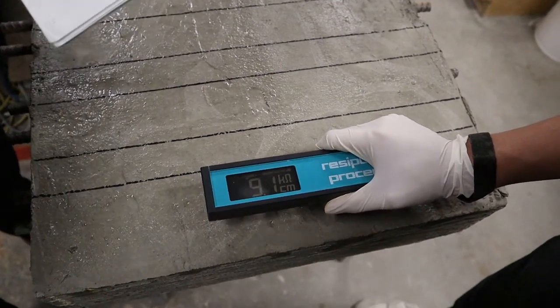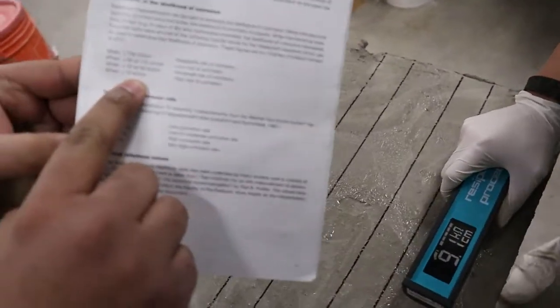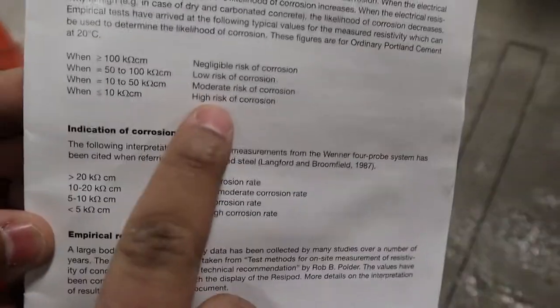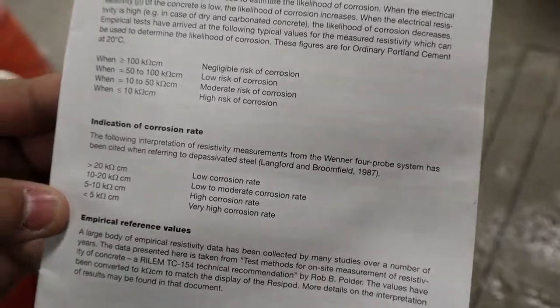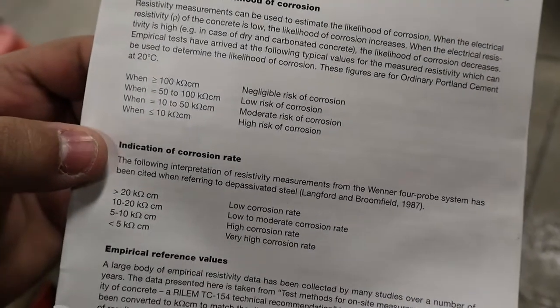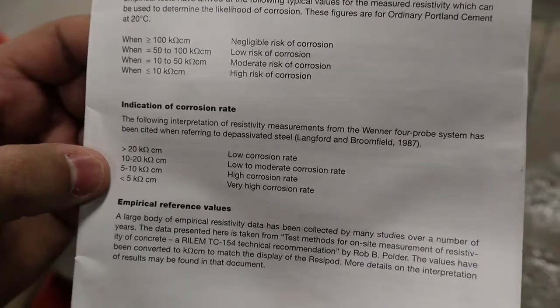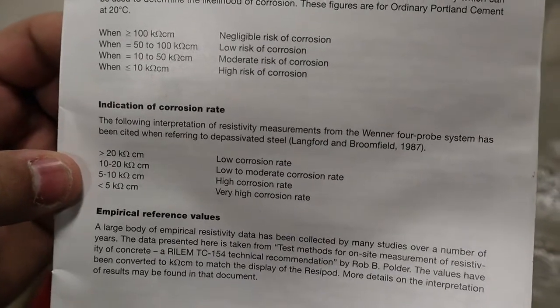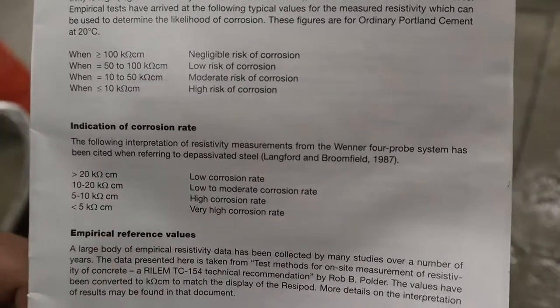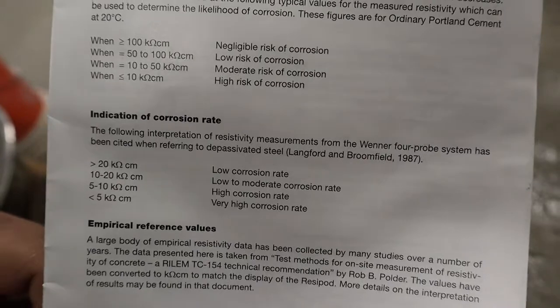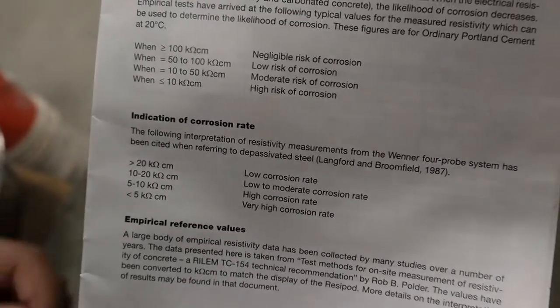As you can see in the manual, it's less than 10 kilo ohm centimeter for the likelihood of corrosion, so there is a high risk of corrosion. Likewise, for the indication of corrosion rate, the range is between 5 to 10 kilo ohm centimeter, which indicates that there is a high corrosion rate in this area. Now my colleague will be conducting the rest of the test.